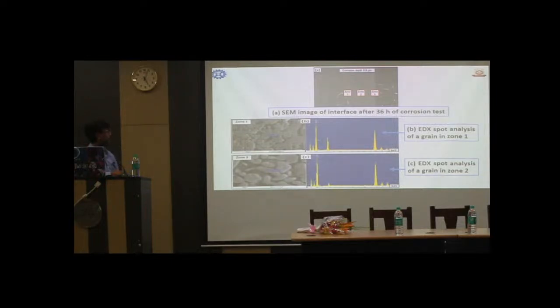I can go through some of the spectrum. Suppose this is the glass, this zone 3 near the glass. If you start, this is the unreacted refractory. Zone 1 is near the unreacted refractory, and you move from zone 1, zone 2, and zone 3 towards the glass. Now suppose zone 1. In zone 1, you see the aluminum concentration is more. It is a point analysis of a particular grain. Aluminum concentration is more, but in zone 2, the aluminum concentration is much less.